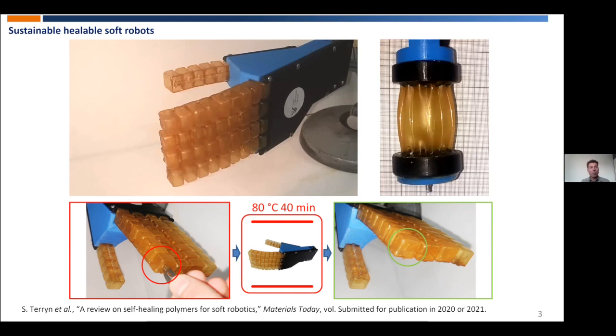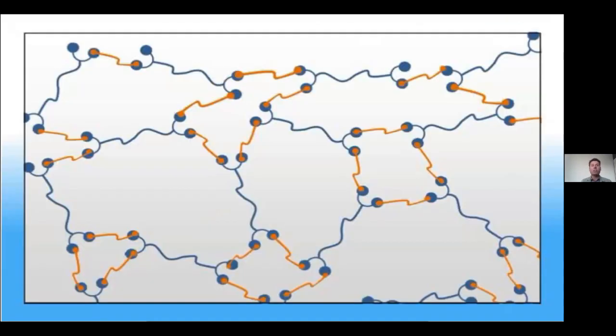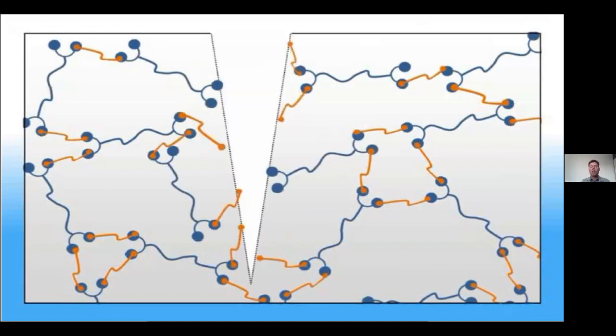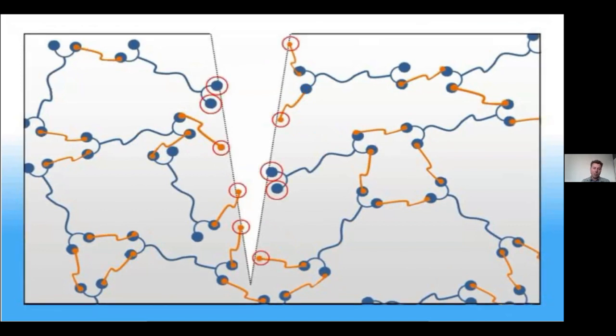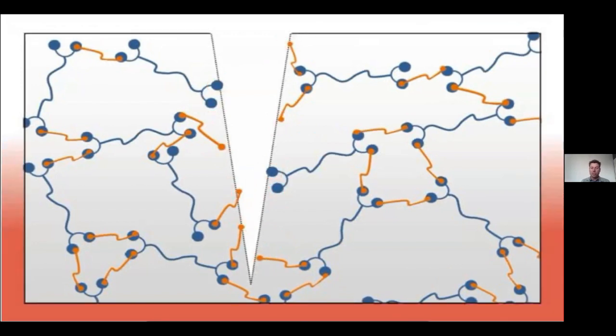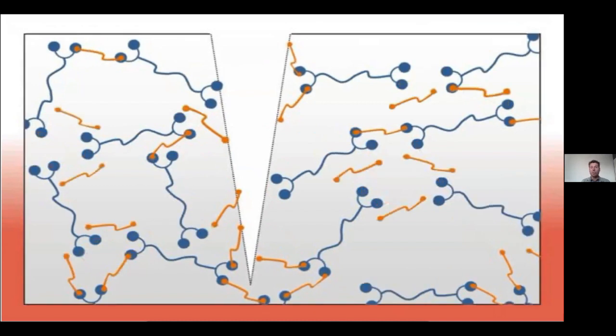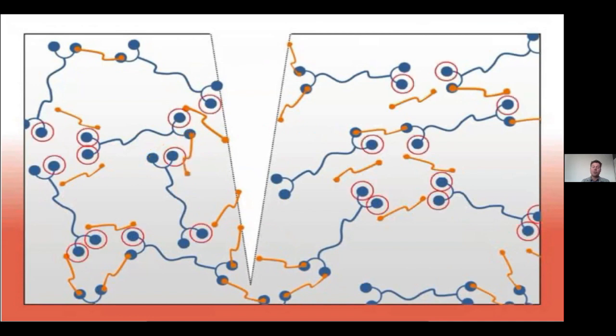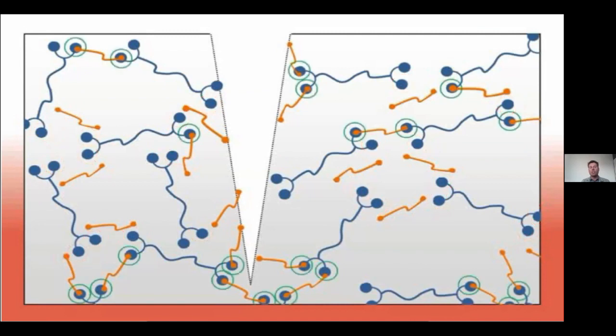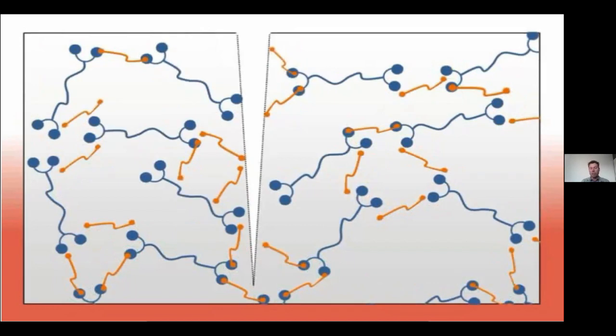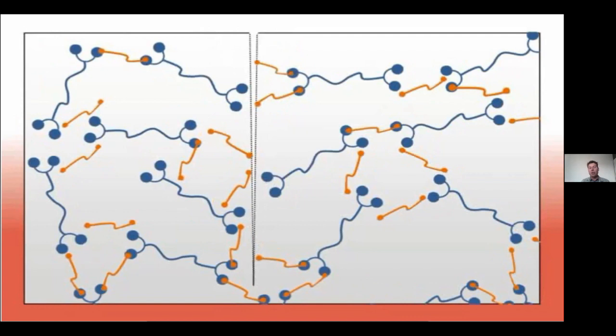Now, how does the healing work? Well, we have a polymer network structure, and in this network structure, the connection points are Diels-Alder bonds, which are reversible. Now, if you cut, then locally you break these Diels-Alder bonds. And if you then want to heal, then we need to increase the temperature. Now, if we increase the temperature, then throughout the network, we will break additional Diels-Alder bonds, and this gives more mobility and also more reactivity. Now, because you have more mobility on the molecular level, you can start sealing gaps on the molecular and microscopic level. So you first seal the gaps, and when everything is sealed, we can actually start decreasing the temperature again.